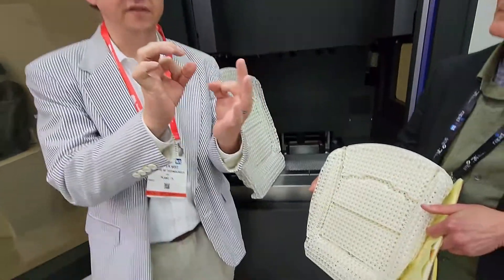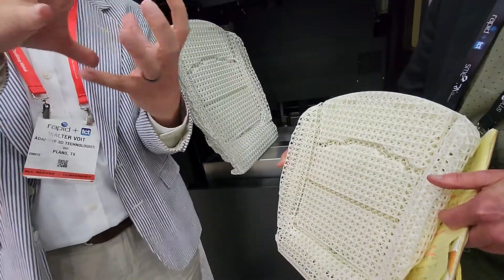When you heat them up to 160°C, they have all the gas — CO2 — that starts blowing up these little balloons. In most foams, those balloons expand until they pop, and then the foam collapses on itself, unless you foam it in a mold.